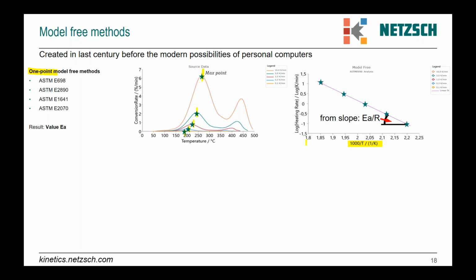It's Arrhenius axis, and vertically logarithm of heating rate, and all these points are on the straight line, and the slope of this line is proportional to activation energy. So we take maximum points, put them here, and find one value. Result is only one value of activation energy.